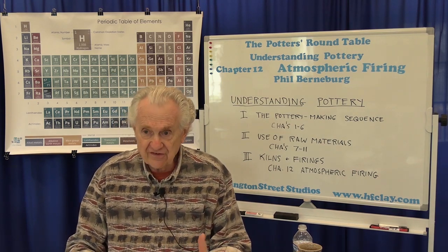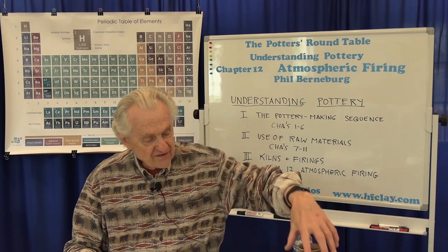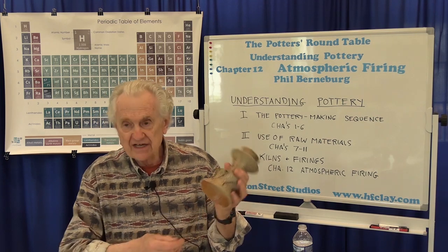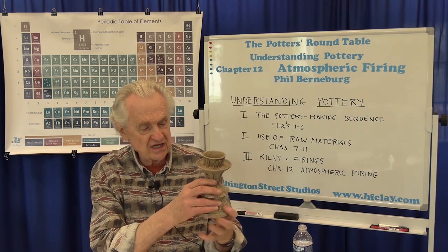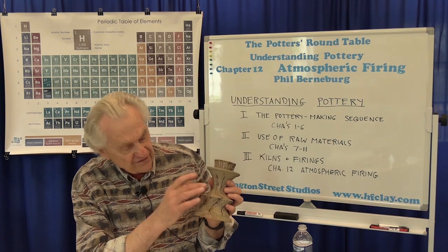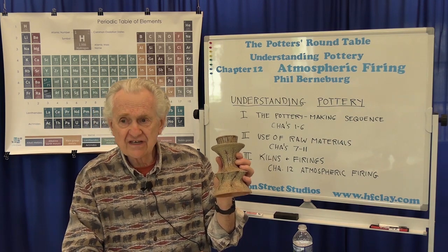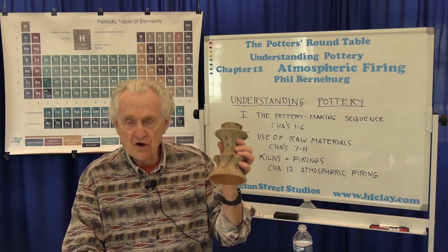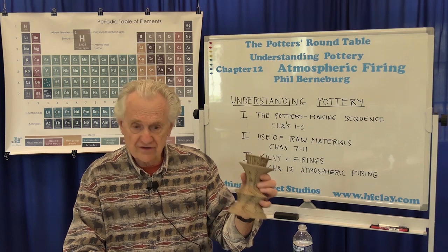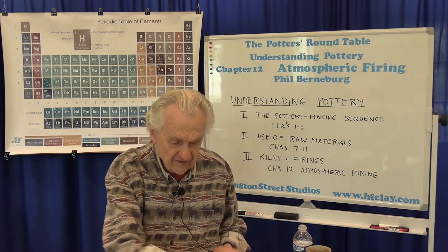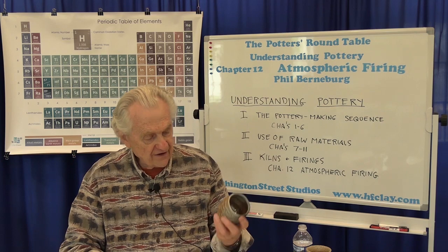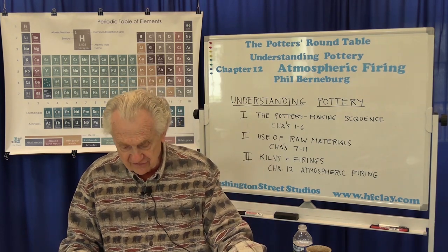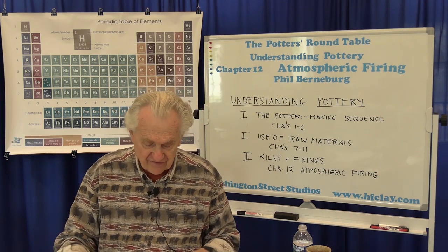There's a slightly different surface texture from soda firing, which is not as bumpy. This is an example of a salt-fired piece — a light gray stoneware — and you can see a combination of flashing but also a sort of spotted texture on the material. That's the classic salt-fired texture, known as orange peel texture. You don't get this same kind of texture from sodium bicarbonate soda firing. You tend to get more just a smooth, glassy coating, a little less of the bumpy texture. But basically, other than that, the effects are the same. The soda technique, like the salt, is used with both wood and gas.